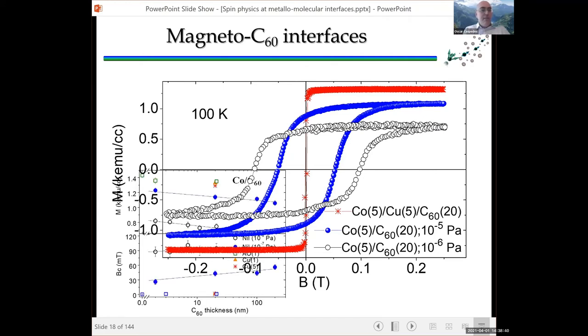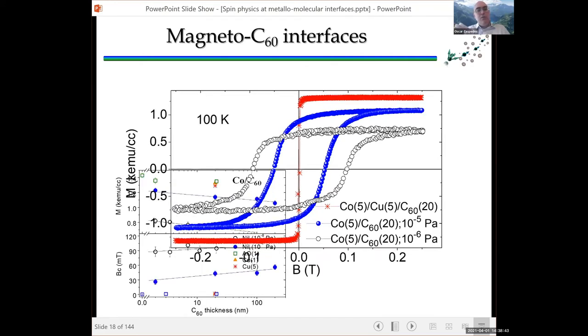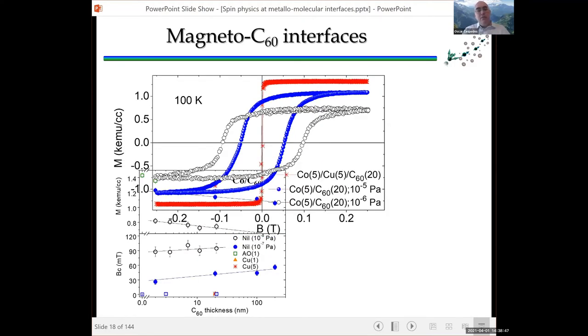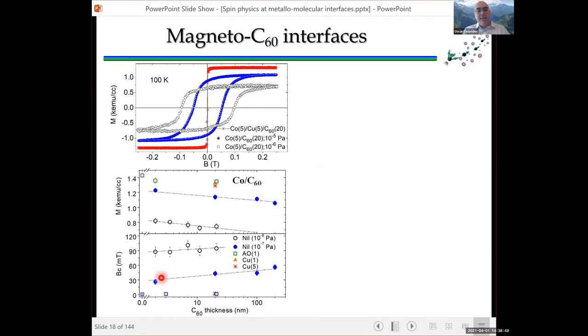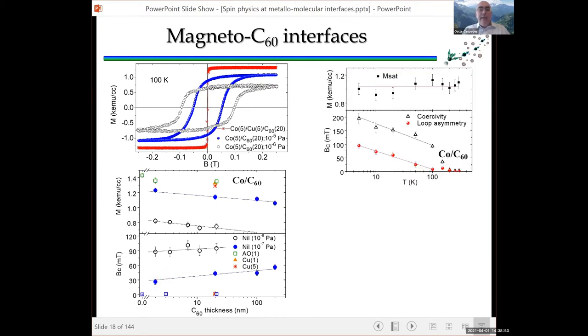The other surprising thing we saw is that these effects propagate to very thick molecular layers. So as you make your C60 thicker and thicker, you see bigger and bigger effects. And this extends up to several hundred nanometers. But these effects only kick in at about 200 Kelvin. And you don't really see them so much with iron and nickel. You still see them, but they are much stronger in cobalt.